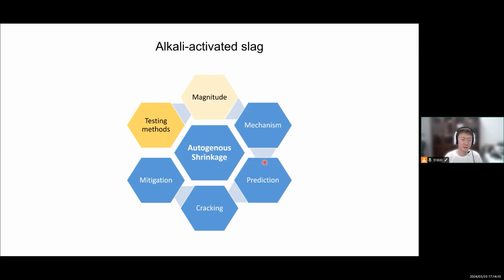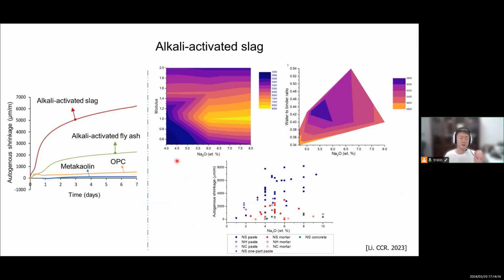So the testing methods are basically fine. And then I went to the magnitude part. We can see that there are a lot of parameters that influence the magnitude of autogenous shrinkage of AAS. Basically, if we use a lot of alkalis, there will be higher autogenous shrinkage. But for the modulus, it's not the higher the larger shrinkage, but somewhere around 1.5. If we use a modulus of activator, which means silicate to sodium ratio, of 1.5, the autogenous shrinkage is the largest. And for the water to binder ratio, the trend is the same as for Portland cement. So if we use a lower water to cement ratio, of course there will be larger shrinkage because there will be less water available and also a very dense pore structure.